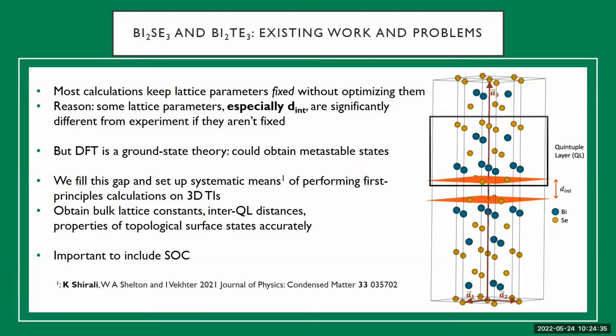So when we started out running our calculations, we found that most calculations keep the lattice parameters fixed without optimizing them. The reason is that some of the lattice parameters, especially that distance between the quintuple layers, are significantly different from experimental values if they aren't fixed, and we optimize them ourselves. However, this is a problem because DFT itself is a ground state theory. So we could end up obtaining what are called metastable states if we end up fixing the lattice parameters.